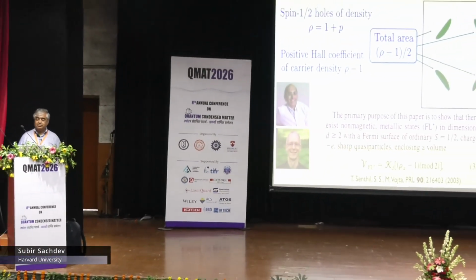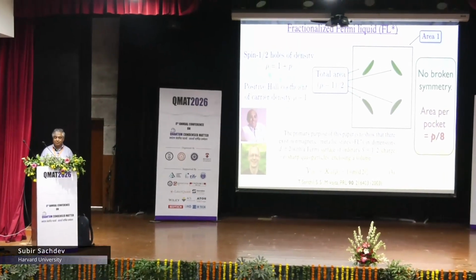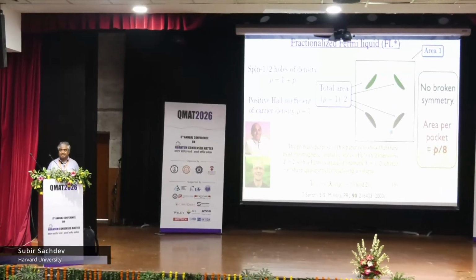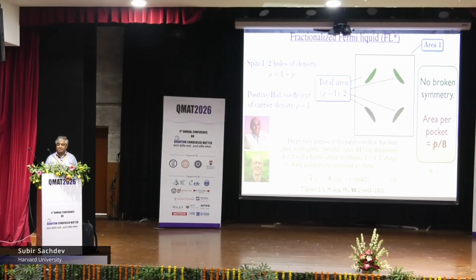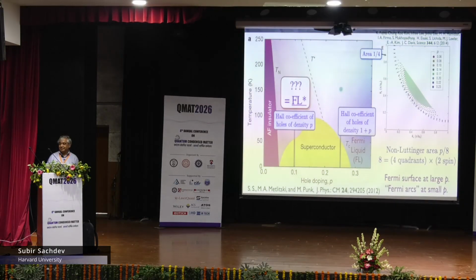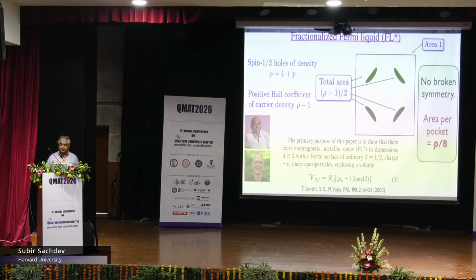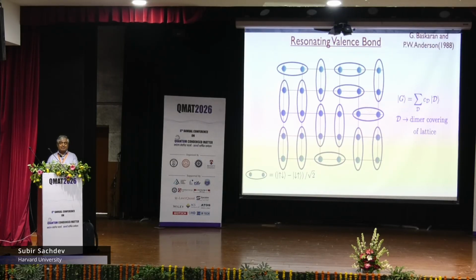So our proposal was that this region is the state we call FL star. And let me just give you very quickly a picture of what this FL star is. This was our statement in 2003 that there can be states of matter that violate the Luttinger theorem. And these states require a very subtle type of entanglement, which is quite different from the entanglement in the SYK model. And I'll show you what it looks like. It gives you a total area enclosed by the Fermi surface that is not the density rho, but rho minus 1. And if you have 4 pockets, the area for a pocket should be p over 8, which is exactly the area that, at least in an ad hoc manner, the STM measurement was measuring here. Okay. All right.